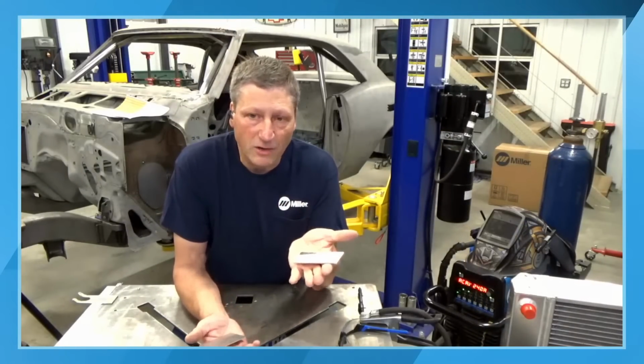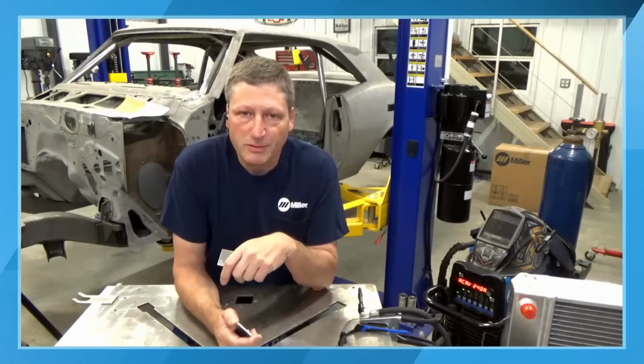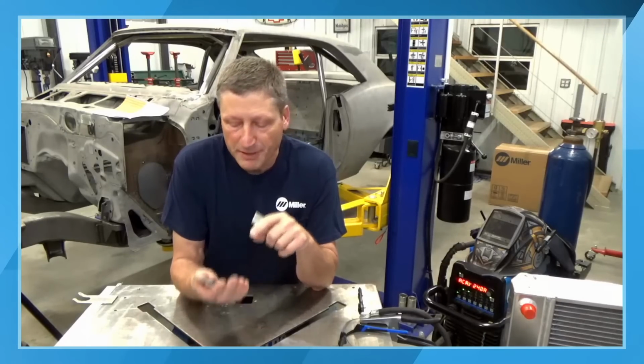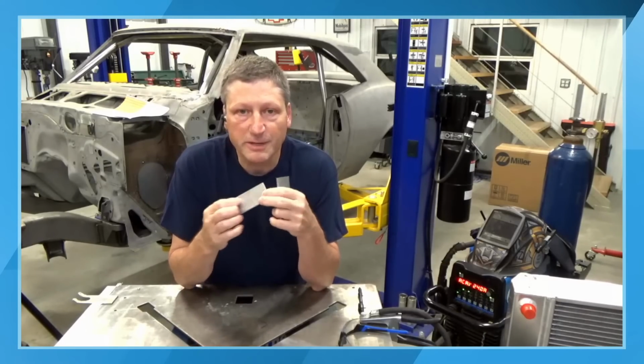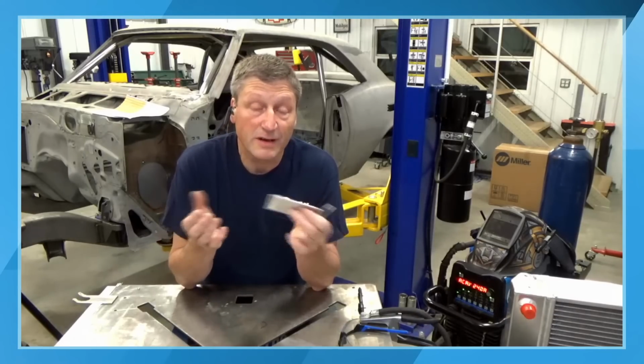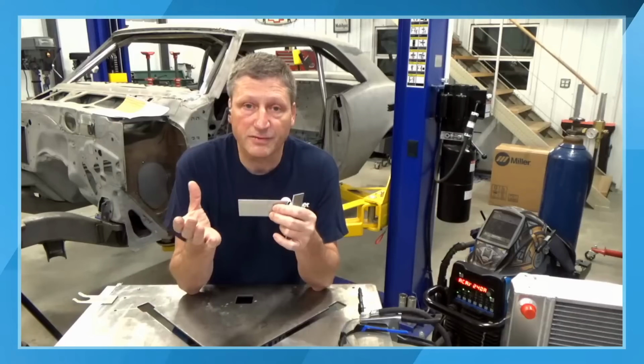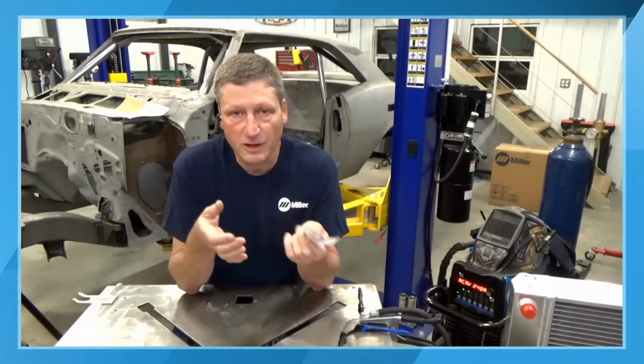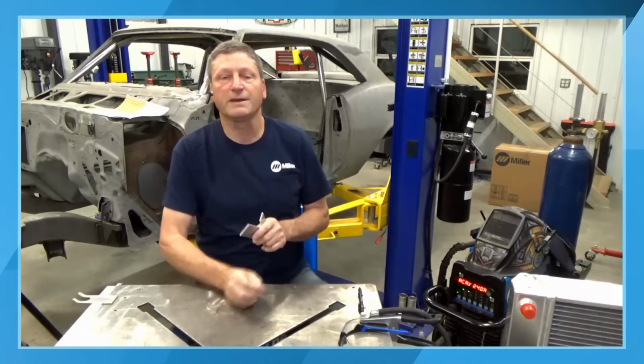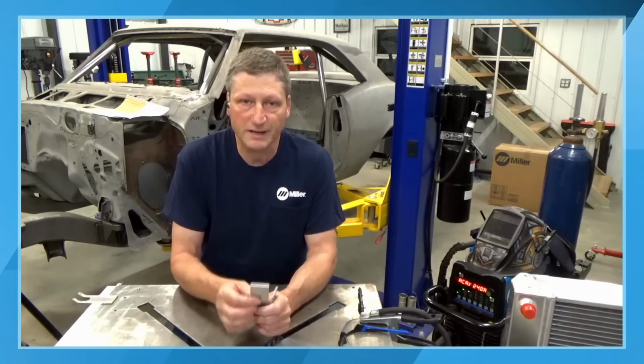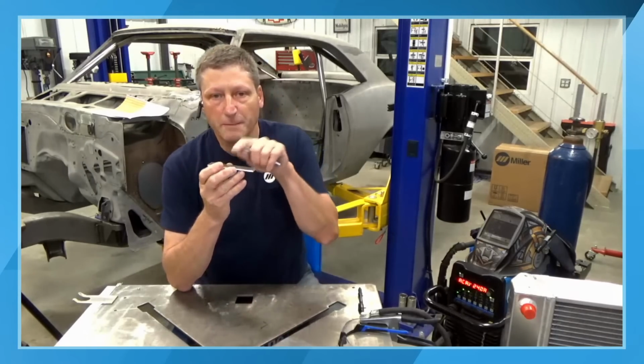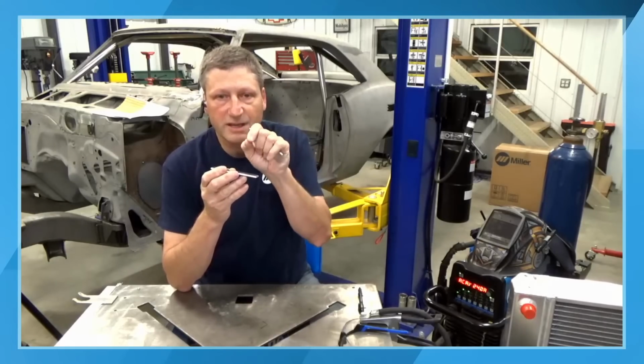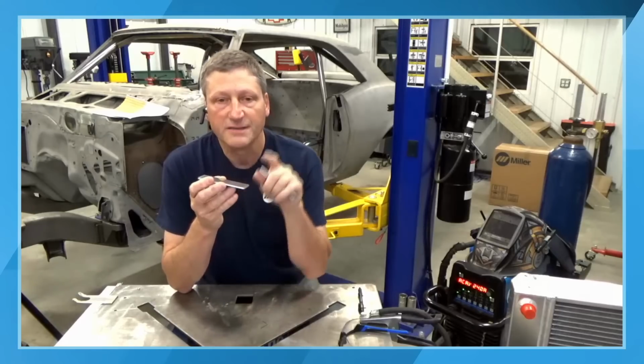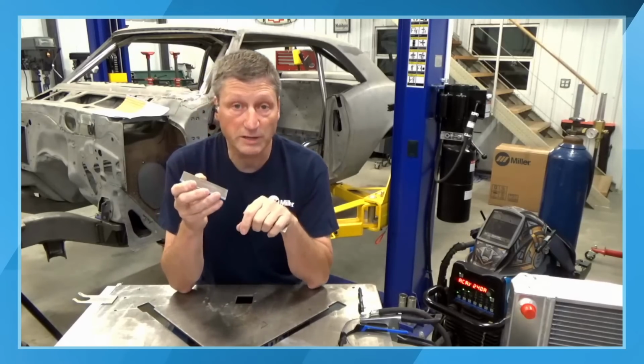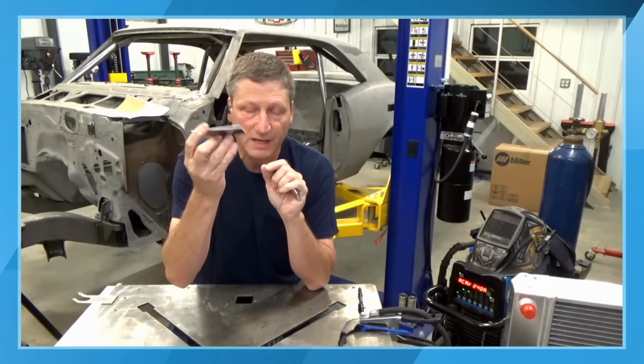Aluminum, depending upon the alloy, melts between 1400 and 1600 degrees. But the oxide layer that forms on the aluminum, 3700 degrees, right? So you have to chip that oxide layer off. So that's why we use AC, or alternating current. And if you were on one of the beginner ones, Andrew probably discussed the effects of alternating current on aluminum. So the positive side of the AC helps chip those oxides off. The negative side of the AC does the welding. That's where the heat goes into the piece.